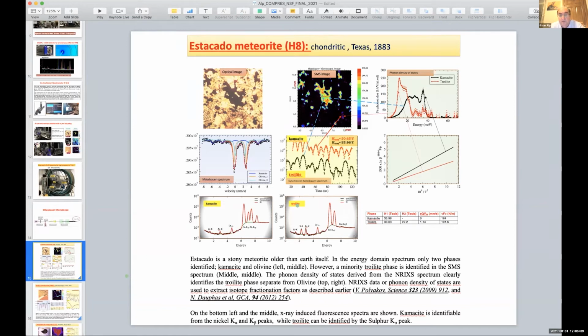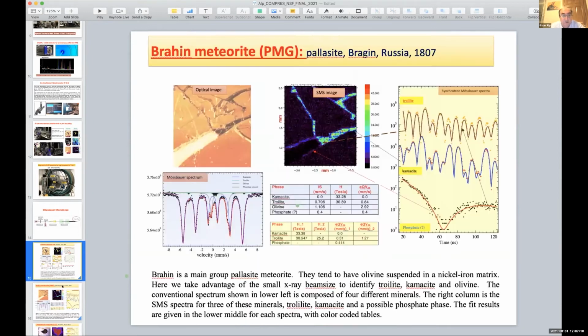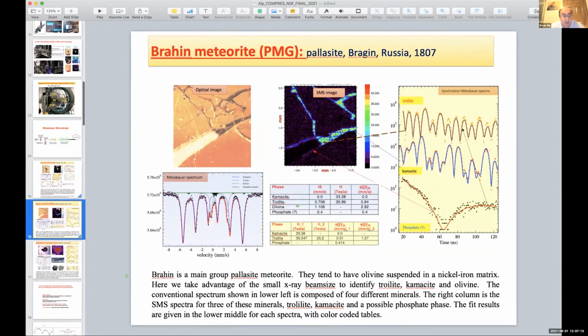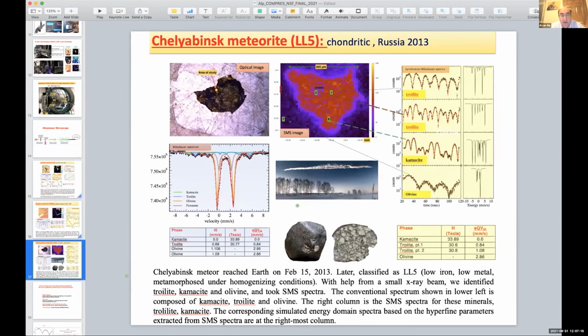So if you go to several different locations on this mineral, on these iron-containing parts, you can get nuclear forward scattering information, and you can separate kamacite from troilite, for example. And furthermore, you can put the detector on the side and record the phonon density of states, which will allow you to determine the temperature dependence of the isotope fractionation. So combined with the fluorescence data and diffraction data, we now have a very powerful tool to study mixed samples. So I looked at a couple of different meteorites just for the heck of it. And finally, somebody handed me the Chelyabinsk meteorite, and I looked at that too.